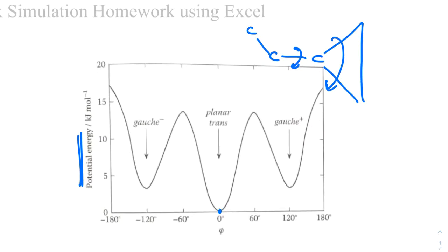And this is essentially what is called a trans position. That's the lowest energy. And then when you rotate, this is by rotating as a carbon here, carbon here. And then they go actually higher. And then they go actually higher. And this is a higher position. And then they go to the gauche. And then they go to the eclipse position. So in this case they prefer these three points. And this is a little unhappy higher energy point.